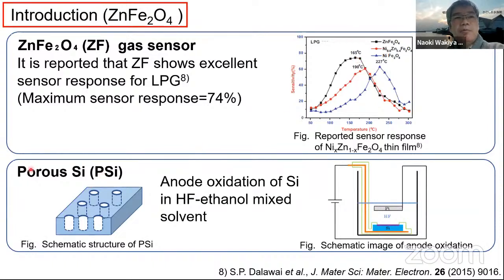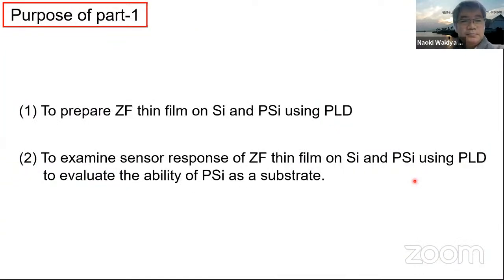And this is a porous silicon. The porous silicon is formed by anodic oxidation of silicon in HF ethanol mixed solvent using this kind of anodic oxidation. And so the purpose of this part one is to prepare zinc ferrite thin film on silicon and porous silicon substrate using pulsed laser deposition. And second, to examine the sensor response of zinc ferrite thin film on silicon and porous silicon prepared using pulsed laser deposition, to evaluate the ability of porous silicon as a substrate for the sensors.